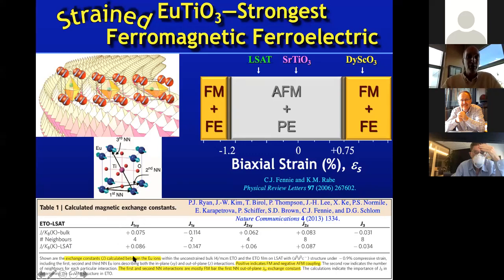Now, a beauty of being able to do first principles calculations is that Craig could calculate what each one of these terms was. And if he looks at both the case of unstrained bulk europium titanate versus, for example, putting it on LSAT, which is going to be biaxial compression, he can see how those exchange constants change with strain. And when he looks at bulk europium titanate, what he sees is that the nearest neighbor exchange interaction, so this is between europium and europium direct exchange, is positive. So it would like to be ferromagnetically aligned.